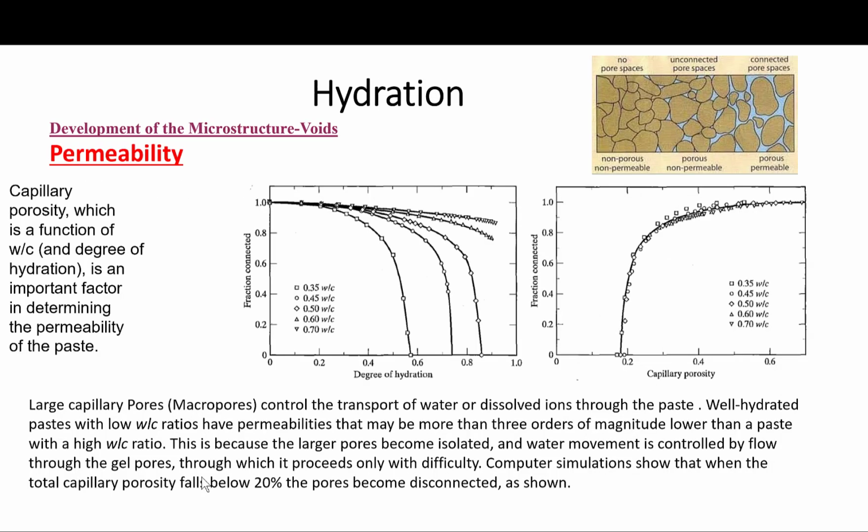So let's talk about the concept of permeability. As we can see here, capillary porosity, as I said, which is a function of water cement ratio and degree of hydration, is an important factor for determining the permeability of the paste.